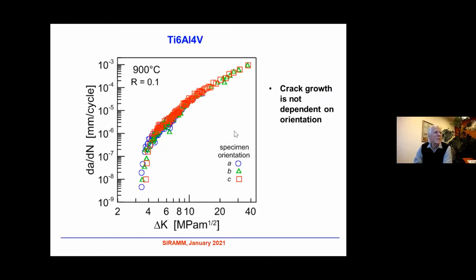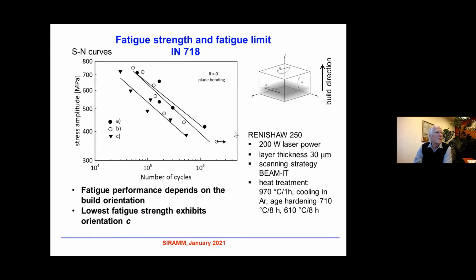Just a moment. It's here. Yes, the whole lifetime is given by changes of mechanical properties during cycling. It is the first stage. Then by crack initiation, and then by crack propagation. And if I have a total life, it is a sum of all these effects. In this case, it is given predominantly by initiation of cracks, and the crack propagation practically plays a very small role. On the other hand, if you have in a component a very long crack, let us say 10 millimeters, then the problem of crack growth is very important, and especially the threshold values.